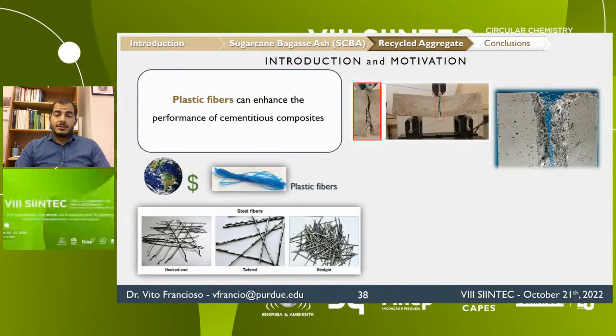and corrosion-resistant. However, the effect on the strength has been reported to be contradictory. It's been observed that the interfacial transition zone, the ITZ, between the matrix and the plastic fibers is affected by the smooth surface and hydrophobic nature of the plastic, resulting in a poor anchoring.